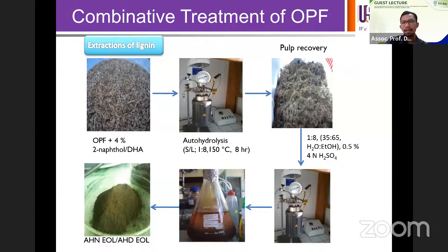the lignin extractability. And after we recover the pulp, we subject it again to the reactor and do the pulping process in order to isolate lignin. And once we get the black liquor, we precipitate it and we can get the lignin powder.